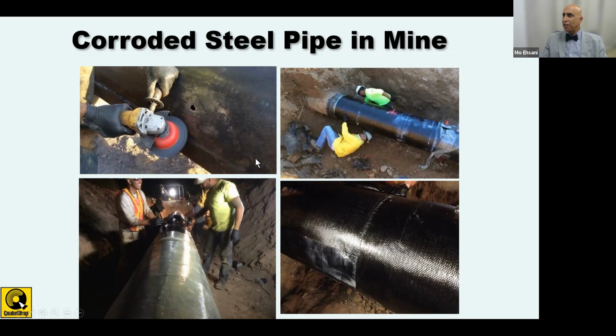So once this is done, by the way, one thing to keep in mind is that you have to make sure that the carbon fiber does not come in contact with steel, because they act as dissimilar metals, and you could have a corrosion process, galvanic corrosion, starting if these two come in contact. So when we are repairing a steel pipe, as was the case here, we first wrap a layer of glass fabric around that pipe. That layer serves as a dielectric barrier. And then on top of that, we wrap the layers of carbon based on the strength and pressure requirements.